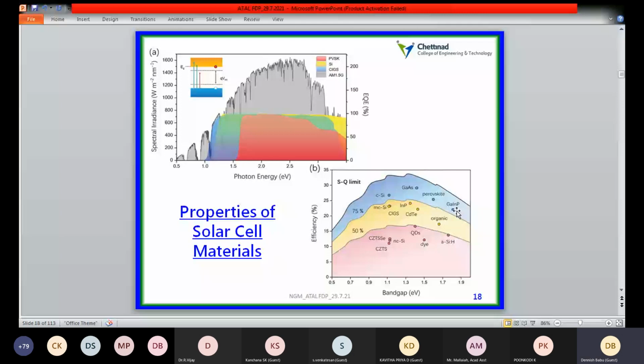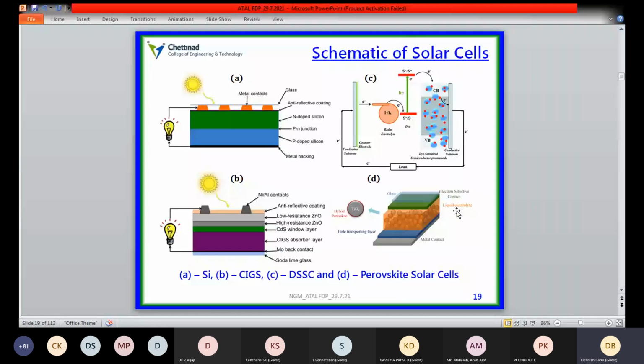Once again, the schematic of a solar cell with respect to the various generations: the diagram depicts the schematic of a traditional silicon-based solar cell. In the structure, people have used a p-type, n-type junction made of silicon-based devices. Above that, they have coated an anti-reflector coating and metal contacts to receive the charge carriers from the device. They have slightly modified this with other p-type and n-type materials like copper indium gallium selenide and cadmium sulfide, and they have used zinc oxide as a low resistance and high resistance layer to receive the charge carriers from the device.